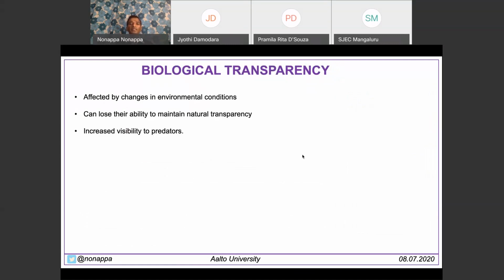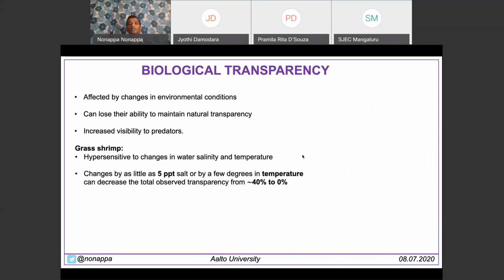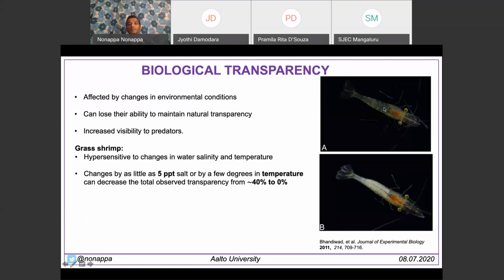But biological transparency is also a challenge because they want to avoid the predators, but they can lose their transparency very quickly. Here is, for example, a type of shrimp, which is highly transparent. But if you take it to a very small change, like 5 parts per thousand of salt, then it loses its transparency and it becomes opaque. Immediately, it will adapt and become opaque and the predator can easily identify.